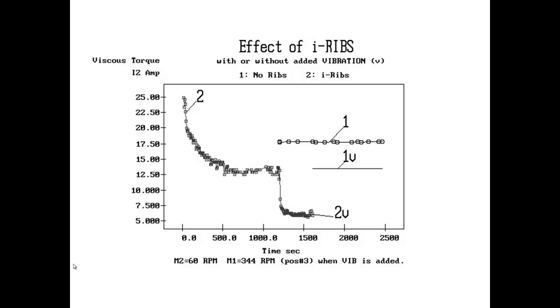And we have several cones which we have built, so here we can compare cone 1 and cone 2. Cone 1 is without ribs, and as you can see here, if we apply only rotation, we have in steady state a certain value of the viscosity, meaning of the torque, and that value is about 18 amperes. If I add vibration to the rotation, for the same cone without ribs, I have reached the level 1V. So we have a benefit of increasing the shear and the strain rate through adding vibration, and we can see that by a lowering of the torque. So this is a boosted shear thinning, if you want.